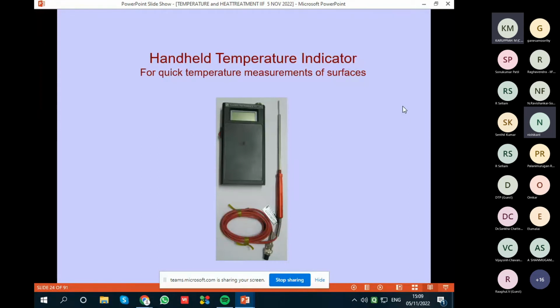If you want to measure any surface temperature of any sand, mold, hot surface, hot plate, anything, it's a handheld instrument, which has got a handle and a thermocouple, a very flat thermocouple at the front end. You can touch it to the hot surface and measure the temperature. It's a battery operated instrument. You can measure up to 1200 degrees centigrade in a couple of seconds. And you can carry it on the shop floor, put it in the pocket, and go anywhere and check the temperature if you've got a doubt.